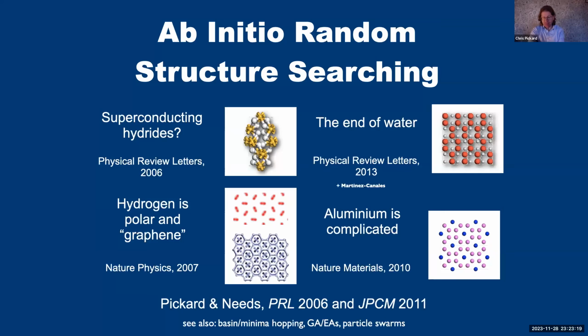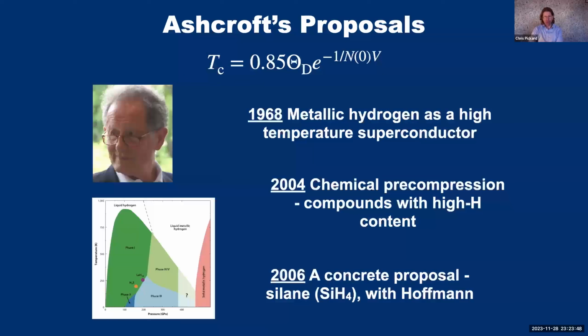And then looking at aluminium, which is a sort of well-known simple metal at lowest pressures, we discovered that there was quite a dramatic phase transition from these simple structures to a complex host-guest, incommensurate, sort of like a one-dimensional quasi-crystal structure at terapascal pressures. And in fact, that result stimulated a lot of interest about the possible richness of behavior of materials at high pressures, at the kind of pressures that experiments like the National Ignition Facility might explore.